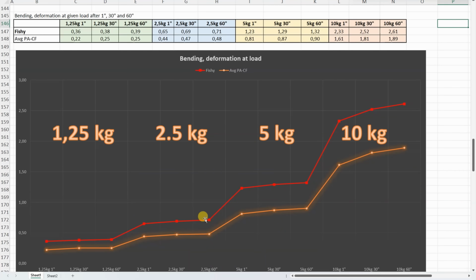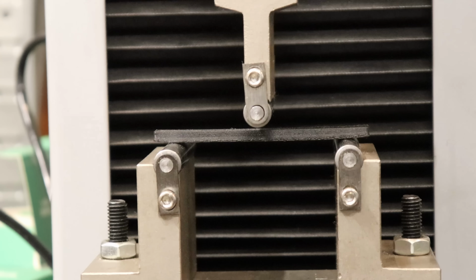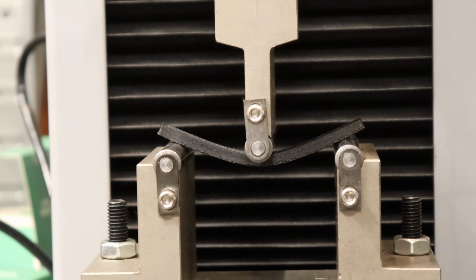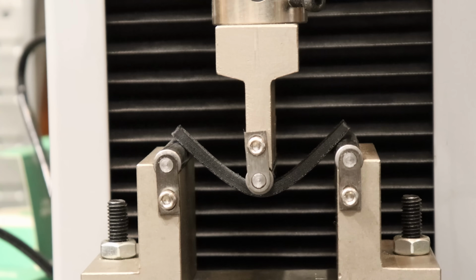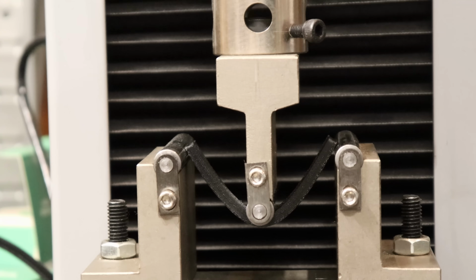Here we can see a little bit bigger deformation of the fishy filament compared to the average PACF, and under 10 kilograms, for example, very similar behavior during that 1 minute, that additional deformation under 10 kilograms. Another 3-point bending test. Distance between supports is 64 mm. This is sped up 8 times.